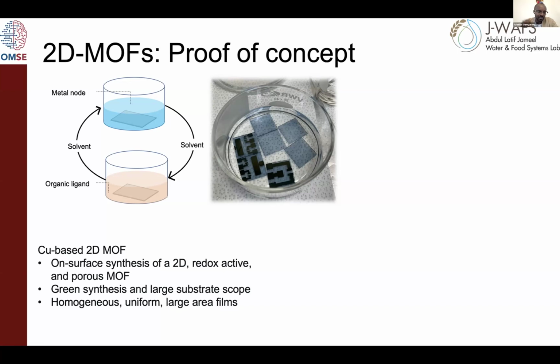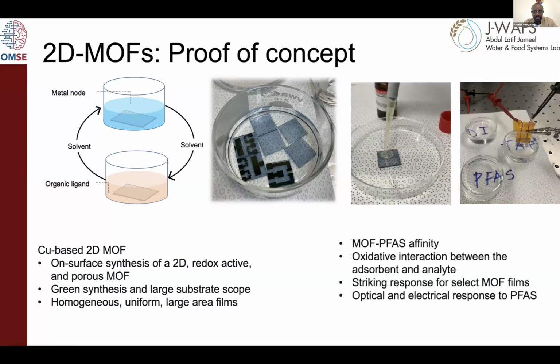We can even use a robot to do this kind of dipping, so we can make thin films down to 100 nanometers thin onto a variety of substrates. We can do ITO, we can do silicon, we can do glass. So we believe that in this case, we're using copper as our metal node, we can make these coordination polymers in a low cost manner. And of course, now we're interested in how they respond.